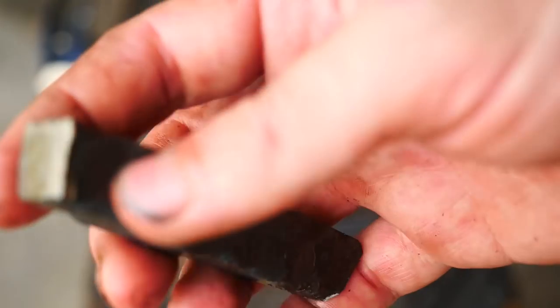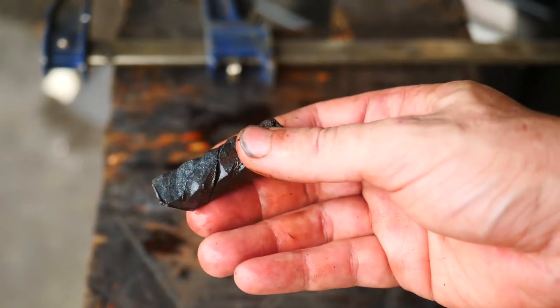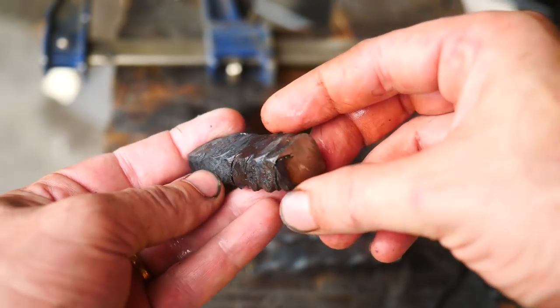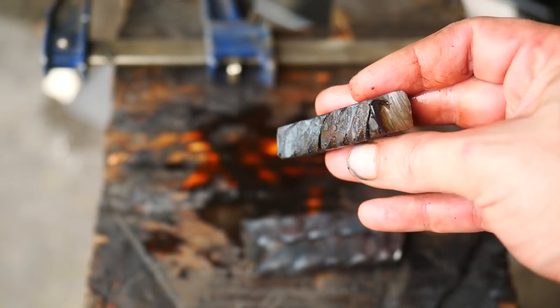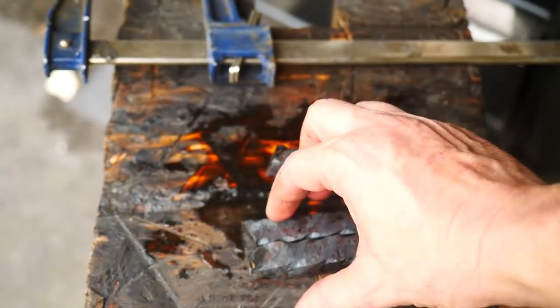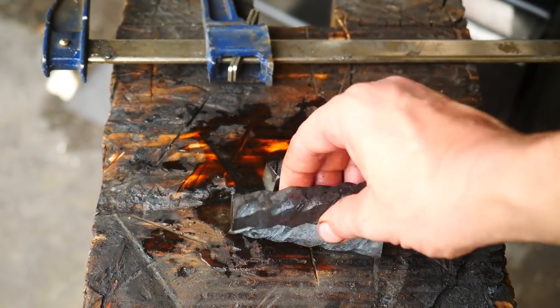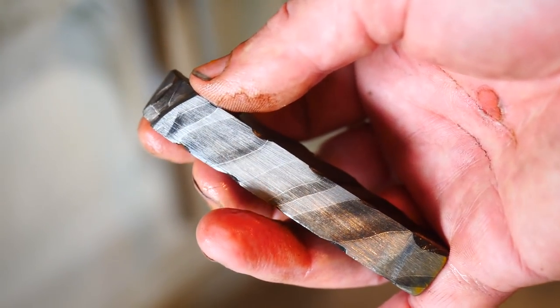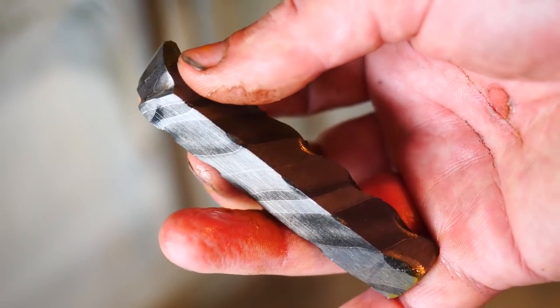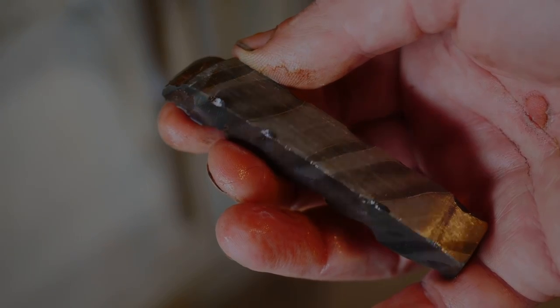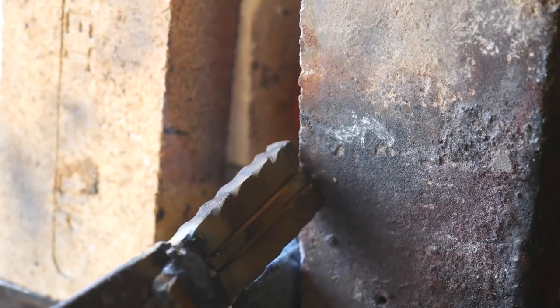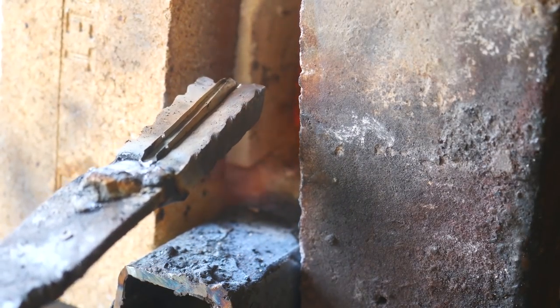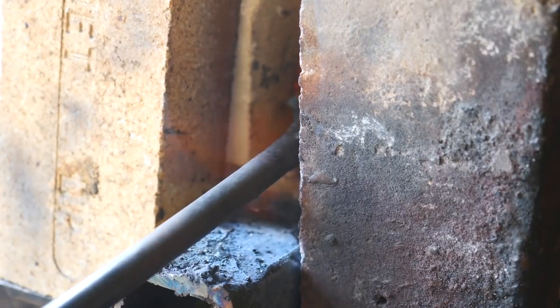Cut it into three pieces. The middle piece was just no good. You can see it here. Some of the twists were a little bit deep and it started to laminate and didn't get welded all back together, so I'm not going to be able to use that piece. That leaves me a little less material than I was hoping for. That's going to be pretty tricky to make something out of. Well, that's the pattern. It's a little bit cooler, isn't it? So I'm going to put a piece of high carbon steel in between it to add some mass, and I got some nickel sheet in between that, so that'll just give us sort of another layer to this pattern.